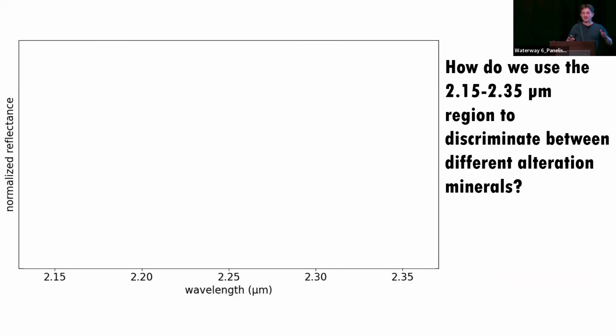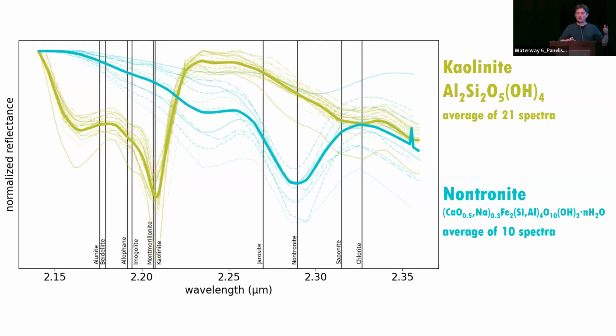But how do we use this region of the infrared to discriminate between different alteration minerals? Here I'm plotting two kinds of minerals that are found in CCS, kaolinite and nontronite. And if we just take a look at nontronite, what you're seeing here is actually the average of all of the nontronite spectra in the USGS and Bishop spectral libraries. And something else I'm doing is calculating the continuum removed band center. That's the minimum wavelength where this band occurs, and actually taking a mean of the band centers of all these different spectra we have, because there is some natural variation that we want to account for. So that's what the vertical black line here is for nontronite, and you can see we've done this for a whole host of relevant CCS minerals.